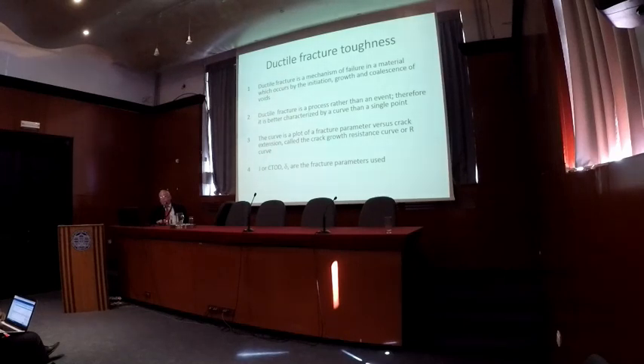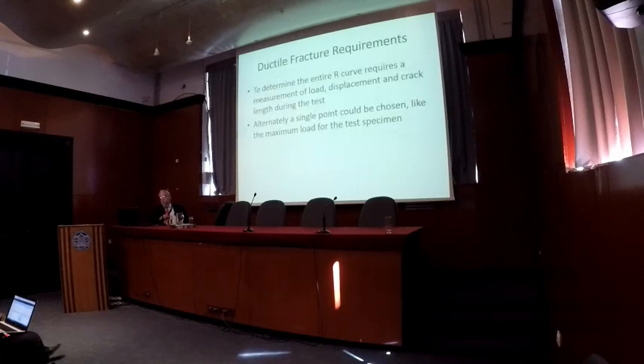So talk a little bit about fracture toughness in ductile behavior. Ductile fracture is a mechanism in which crack growth occurs by initiation, growth, and coalescence of voids. Ductile fracture is a process rather than an event, so you don't have a single point of fracture. Then usually you use an R curve, which is a crack growth resistance curve, to characterize the behavior, and that is a plot of the fracture parameter versus the crack extension. So J or CTOD are used as the fracture parameters, and there's this crack extension.